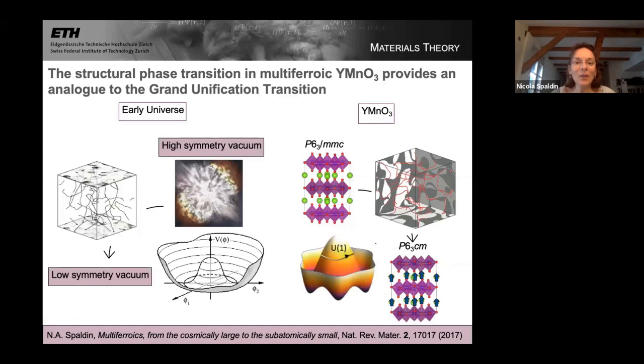Okay, so I hope I've convinced you, or at least I'm going to assert if you're not convinced, that the structural phase transition in yttrium manganite, this transition from paraelectric to ferroelectric, described by the Mexican hat-like potential and giving us one-dimensional domain intersections between the ferroelectric domains, is an analog to the early universe grand unification transition from the high symmetry to the low symmetry vacuum that's proposed to have generated the cosmic strings.